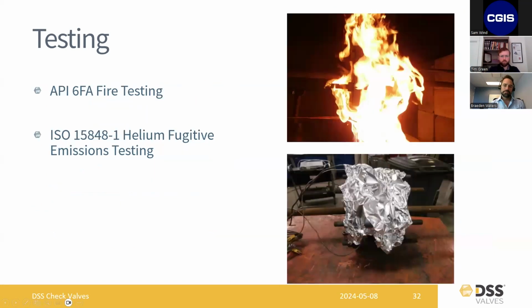So moving on from there, we've also done fire testing. DSS has passed API 6FA fire testing. And this was an important test for our design because it proves that the seat insert, even once this O-ring has gone away, still passes helium leakage tests. So it proves out the design that the metal-to-metal interference fit is good enough to make sure that this valve can withstand exposure to an 1800-degree fire. All elastomers have melted away, and it still prevents fugitive emissions.